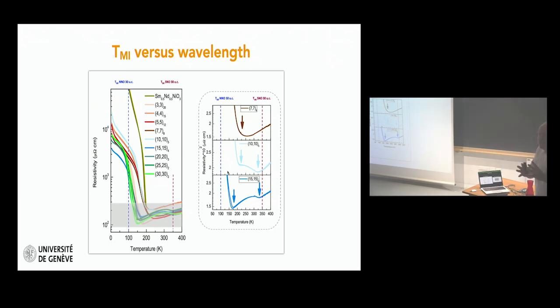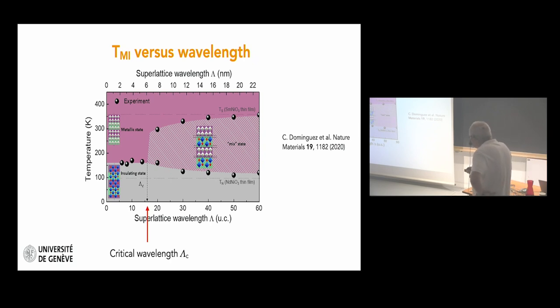But now, when you reduce the wavelengths, you start to see that these two transitions come closer, and at some critical wavelength, you observe only a single transition. And this is what you see on this slide. This is temperature as a function of the superlattice wavelength. You see that for short wavelengths, below this critical wavelength, which is about 16, the sample is entirely metallic and turns entirely insulating at this transition. But if you have thicker layers, you have a metallic state, then a state where one of the materials is insulating and the other one is metallic, and finally they're both insulating. And when we saw this at first, we thought, okay, maybe this is simply this coupling of distortions.